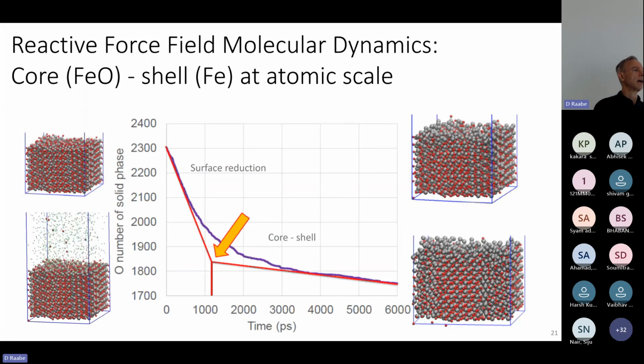In another reactive force field MD simulation, you can also see that when you have formed the first tiny iron layer at the surface, as you can see here on the right-hand side, these silver-colored atoms are the iron that forms after a few layer reduction step at the surface, and act as a core-shell structure. And that means that directly after the first iron shell has formed, you must bring the oxygen outbound through that already reduced iron, and you have a change in the overall kinetics. I found that quite interesting to even see that very quickly here at the atomic scale.